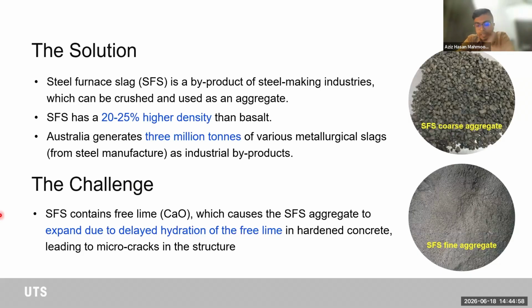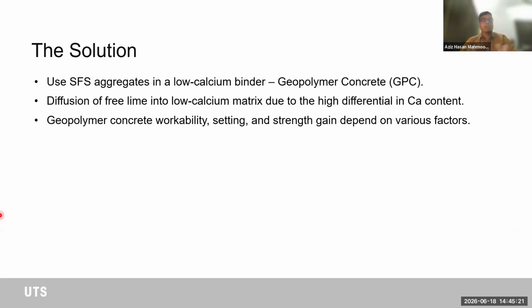So with any kind of expansion within your concrete matrix, it does pose a level of stress that can introduce some cracks within your concrete, and also deleterious chlorides and sulfates and carbon dioxide can impregnate your concrete and really hamper the quality of the concrete. So as a solution, we came up with the idea to use steel furnace slag in a low calcium binder.